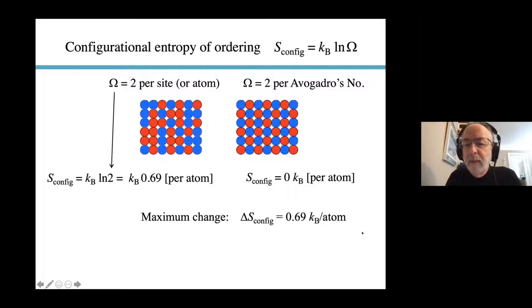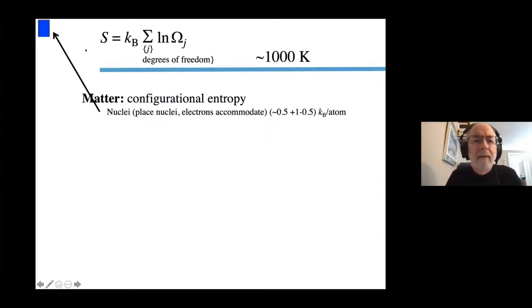And this is quite well known. It's usually less than that, though, because we have some short range order even when we're disordered. So let's put that on a graph here, and I'll lay out more contributions from degrees of freedom in a material. At about 1,000 Kelvin, here's how big a part the configurational entropy will occupy. That was 0.69. I'll say it's between 0.5 and 1.5 in what are called high entropy alloys, where you add a large number of different chemical species.